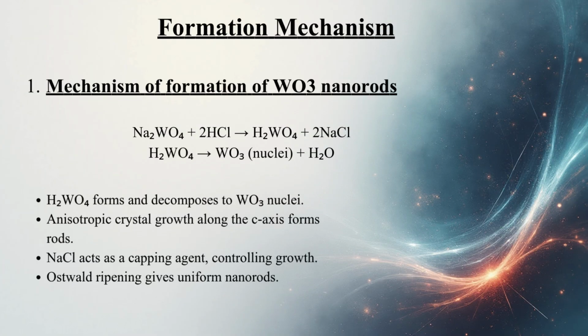Formation mechanism. The chemical route for WO3 nanorod formation via the hydrothermal method: Na2WO4 reacts with acid to form H2WO4, which then decomposes into WO3 nuclei. The rods form through anisotropic growth along one crystal axis, with NaCl controlling the growth and Ostwald ripening ensuring uniformity.